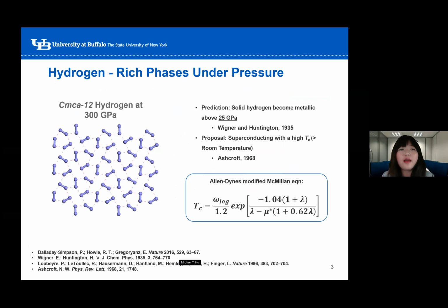So why focus on hydrogen-rich materials? In 1935, Wigner and Huntington predicted that hydrogen can become an alkali metal-like monoatomic solid above 25 GPa. However, later studies suggest that the metallization pressure is much higher than that. In 1968, Ashcroft proposed that this solid hydrogen could become superconducting with a high TC value, potentially higher than room temperature. However, the superconducting transition temperature has not been accessed in experiments yet.